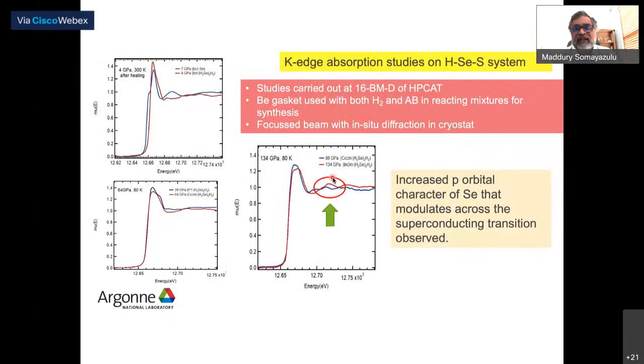Okay, in fact, we did K-edge absorption studies. Again, you can do these at HPCAT. We can do the absorption spectroscopy. And what we do see is an increased p orbital character of selenium that modulates across the superconducting transition. So it's telling us already that this cage is not only stabilized by the central metal atom, there is a certain amount of modulation of electronic structure across the cage by the central metal atom, telling you that you could, in principle, manipulate that central metal atom in whatever way you want from theoretical calculations and modulate the transition temperature.